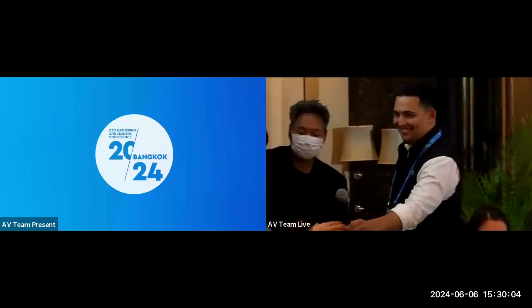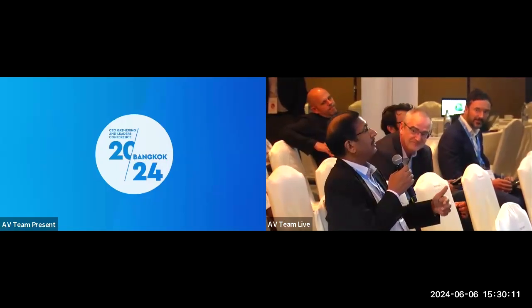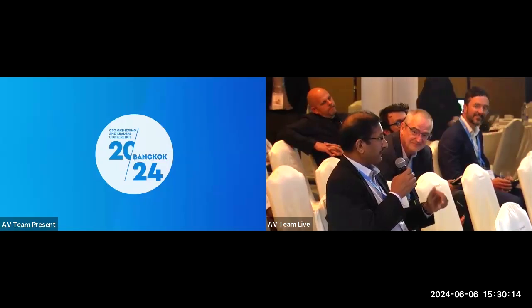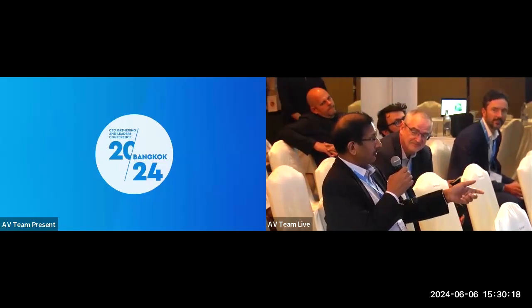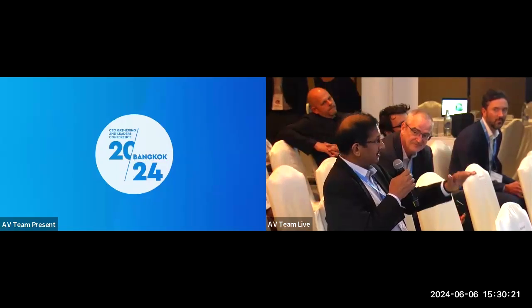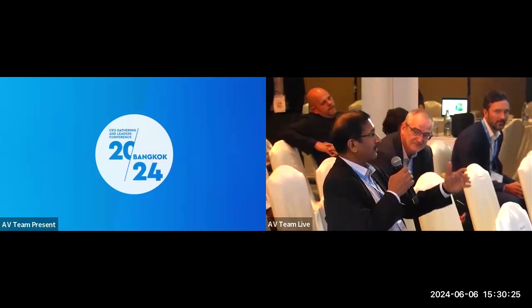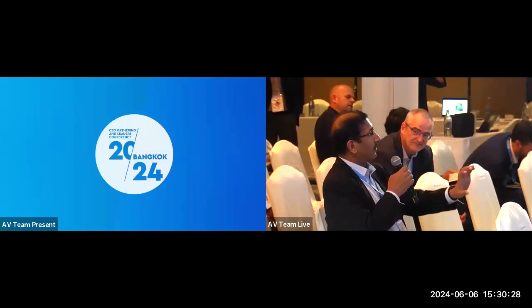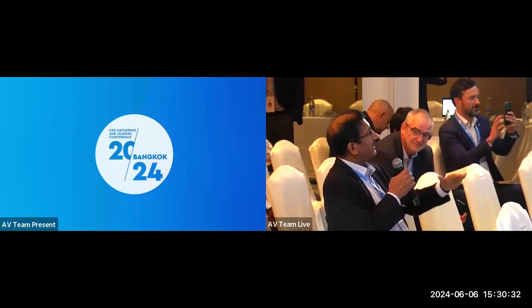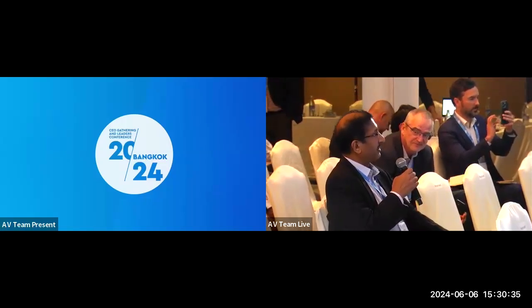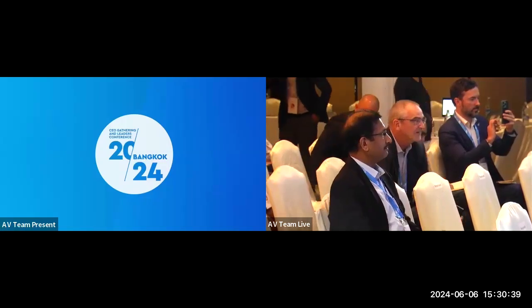My question is for Neocrete. So we understood your activator is used along with pozzolanic material or slag. What if we do not use these pozzolanic materials or slag, directly reducing cement consumption? For example, for achieving some specific strength, we are using 300 kilograms of cement in 1 cubic meter of concrete, and we want to reduce cement consumption to 200 kilograms. So the question is, can we use the activator without the pozzolanic material and just reduce cement content? Exactly. Yeah.